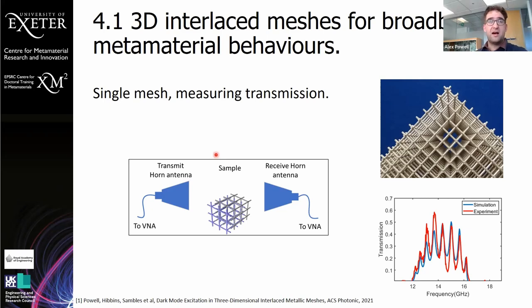But I think that's where the future of it has to lie if it's going to be something that we're going to use. But still, it doesn't get you around the surface roughness, because the best way to 3D print this with metal is still going to be powder sintering. So you're still going to have the surface roughness, and it remains to be seen if that's the limiting factor or not, I think. Okay, I see. Thank you.